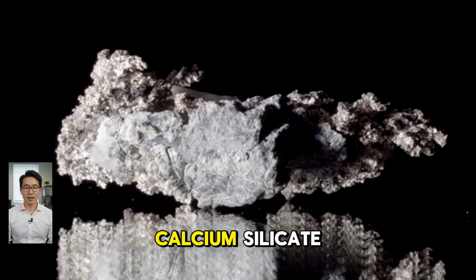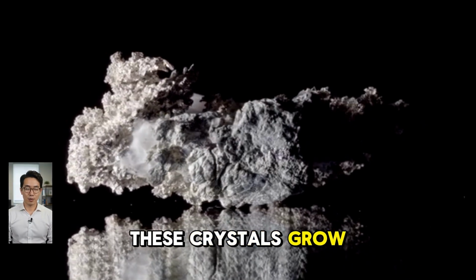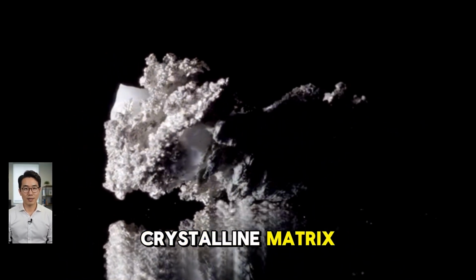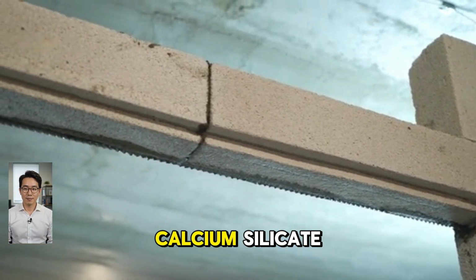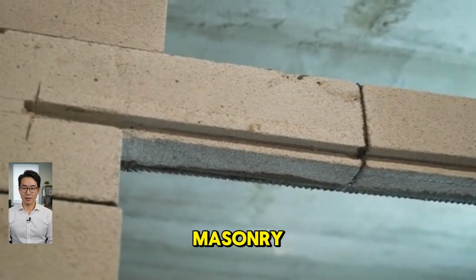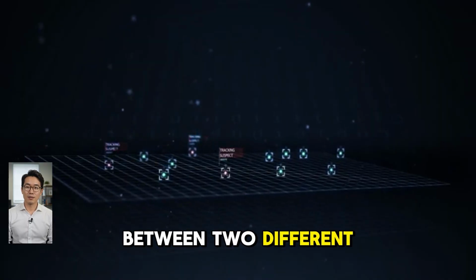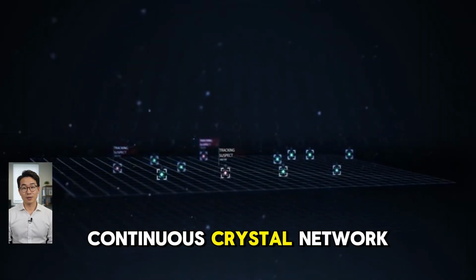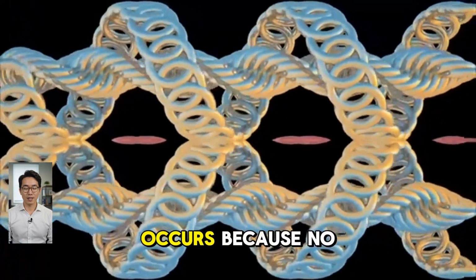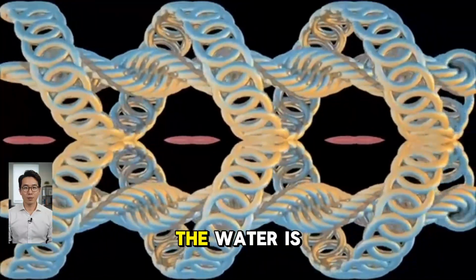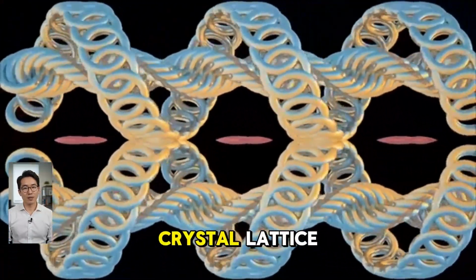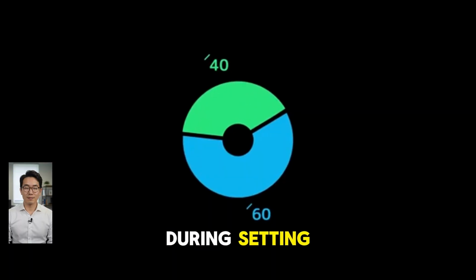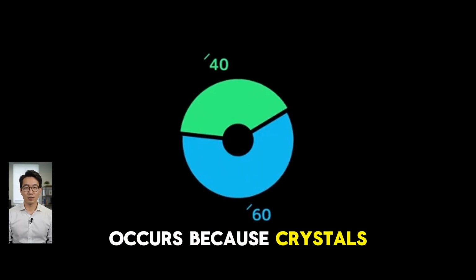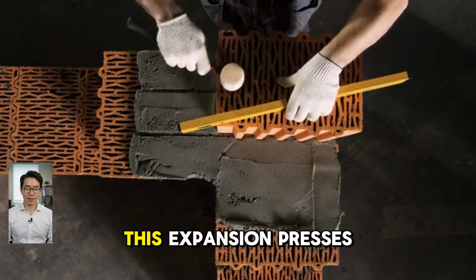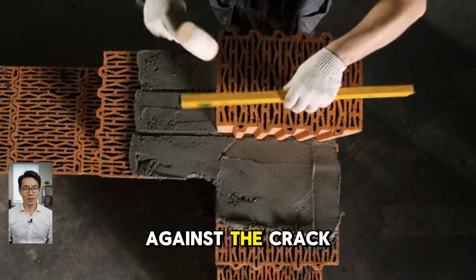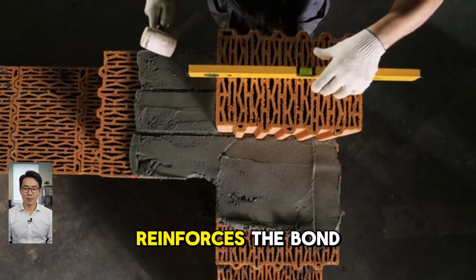These ions precipitate calcium silicate hydrate crystals. These crystals grow and interlock, creating a rigid crystalline matrix. It is chemically bonded to the calcium silicate hydrate crystals in the surrounding concrete or masonry substrate. The bond is not between two different materials at an interface. It is a continuous crystal network that grows without interruption. No shrinkage occurs because no water evaporates. The water is converted into structurally incorporated water in the crystal lattice. The slight expansion during setting, typically 1 to 2%, occurs because crystals occupy more volume than the reactants. This expansion presses the repair material outward against the crack walls, creating compressive contact that reinforces the bond.